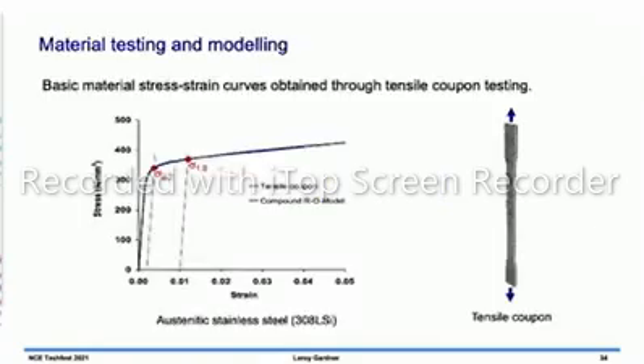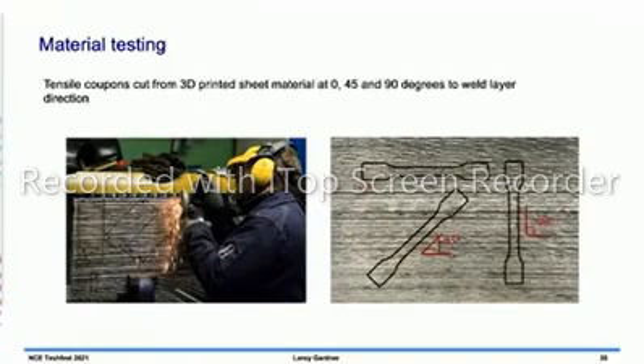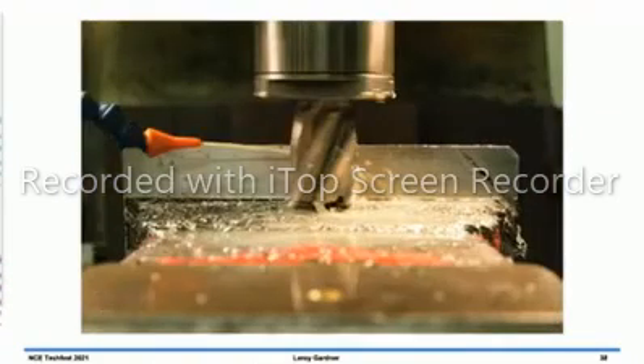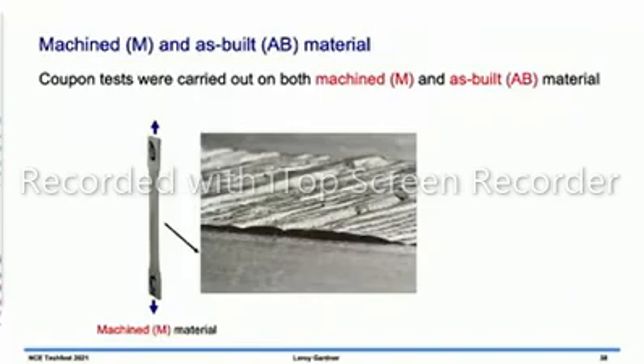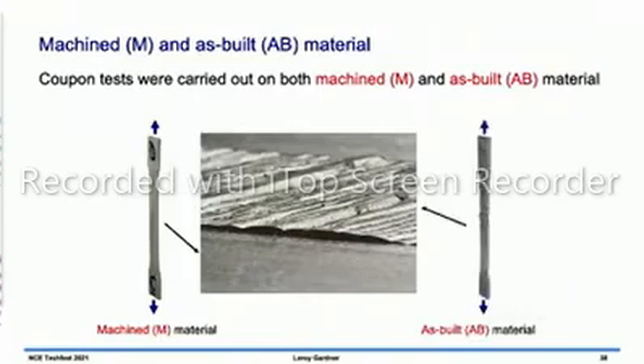So what have we done? We've been testing the material of it. So we've taken some plates, we've cut out some coupons, and we've looked at their stress-strain characteristics. We thought there might well be a directionality to the properties, so we tested material in different directions relative to the print layer direction. We also thought that the surface undulations might have an effect on the performance, so we milled down the surface to make it smooth, so we could compare the behavior of the machined material and then look at the influence of the surface undulations as well.